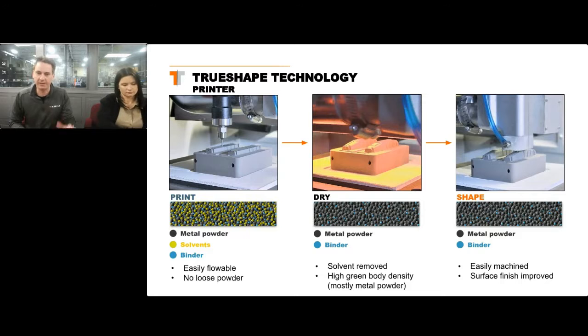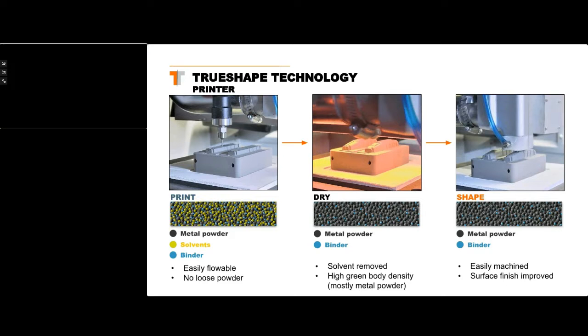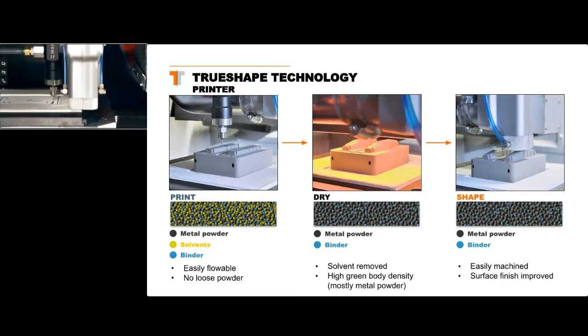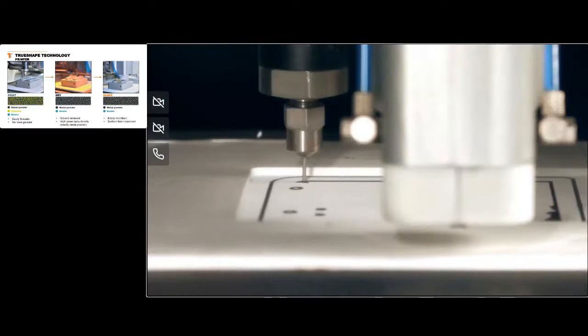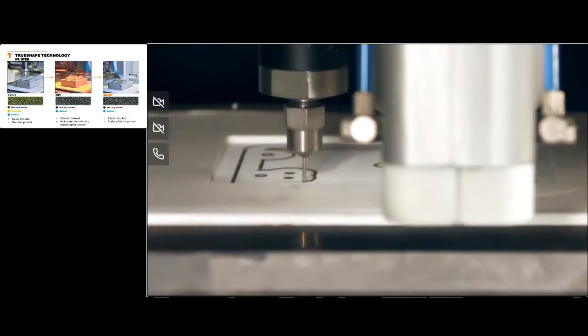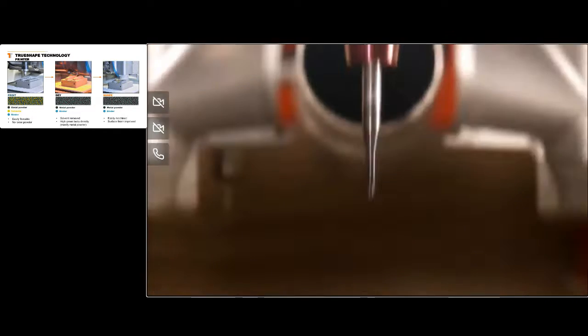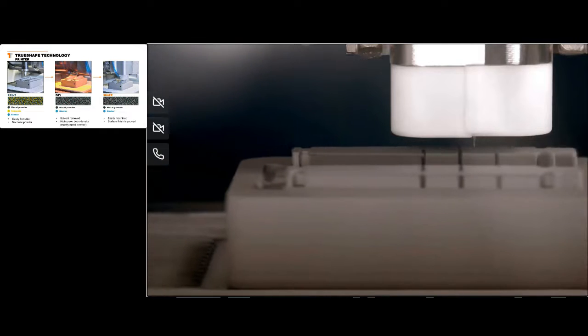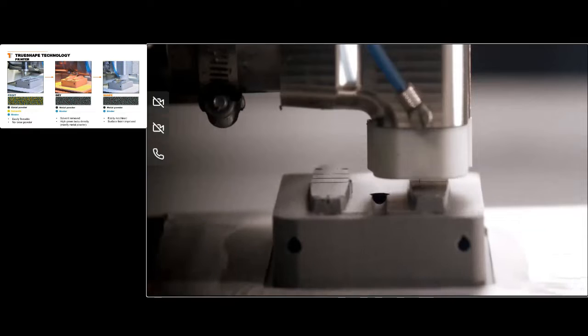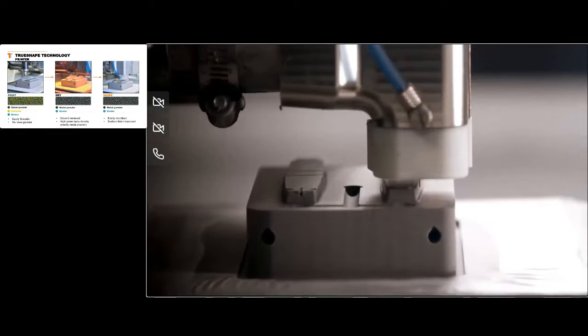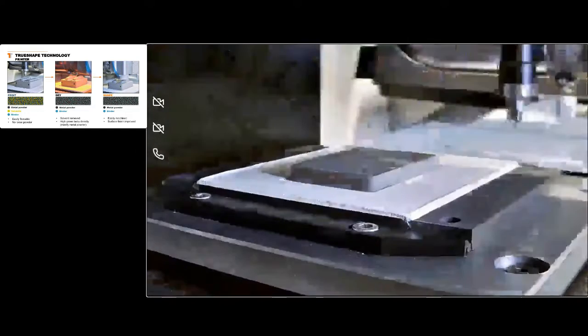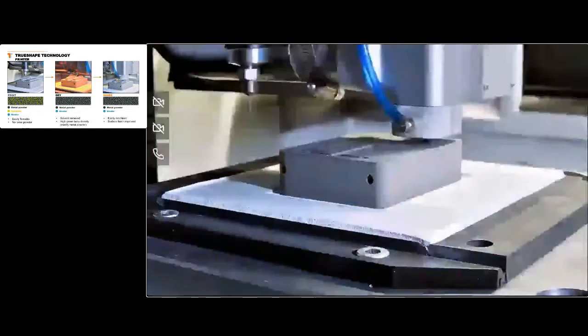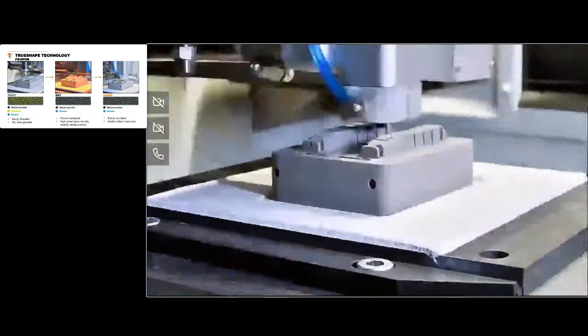I have a quick video here to show how this is actually working because it can be a little bit complicated. But you can see, laying down that paste material, we're just flowing that out onto the build plate. We're going to come through and dry that material, and then we're going to go through and machine. So every layer we're machining flat, every 10 layers we're doing that contour milling step to refine the feature resolution. We can even add in shapes that weren't possible to print because we're just going to machine them in. And you can see, obviously, these steps are going to repeat over a couple hours, couple days, et cetera, to build up the part. But all of that, of course, is completely unattended.